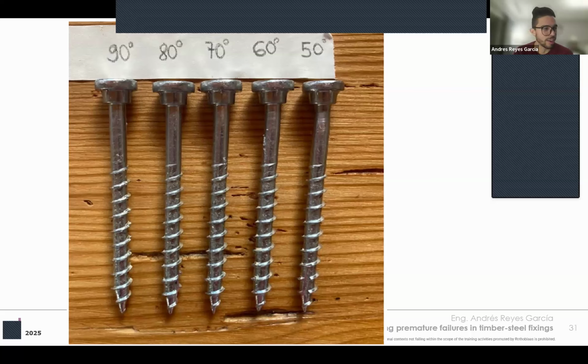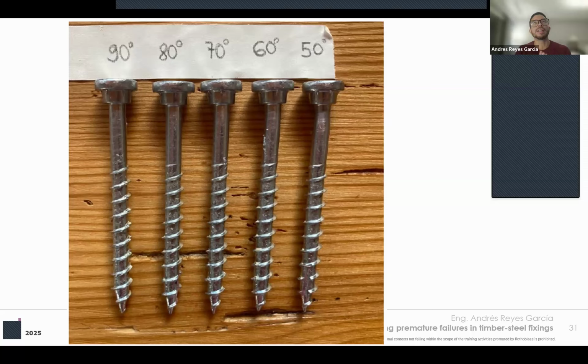Well, yeah, if I had to choose for a very quick, direct answer, the long-term effect that is most important is the moisture management, definitely by far. Because the effect of over-torque, for example, we saw that you have some relaxation over time. So you might have some damage that you induce to the screw, but if there's no corrosion over time, if there's no presence of hydrogen, it might not necessarily lead to a weakening of the fastener. So it might be an elastic deformation or something that the screw was able to sustain because of its robustness. Generally, of course, they have a lot of safety factors inside the screw. Same for the effect of unintended stressors, and also the manufacturing processes.